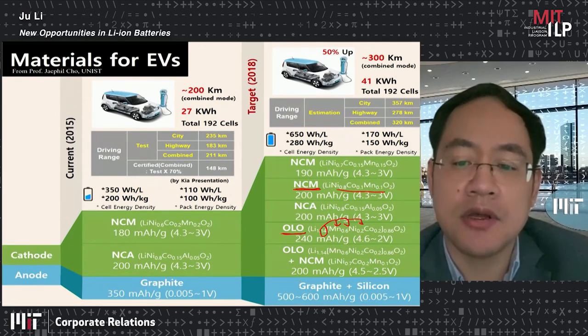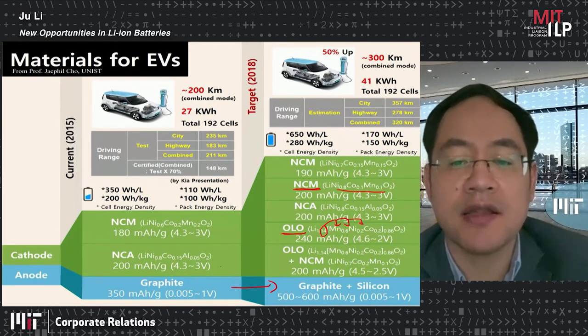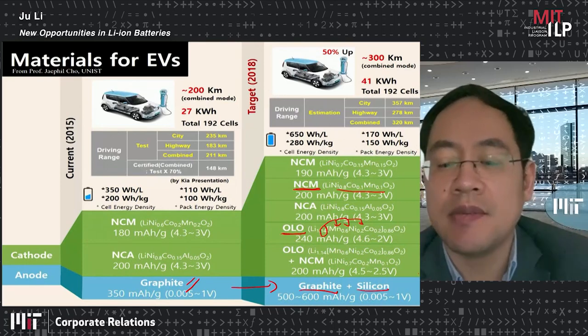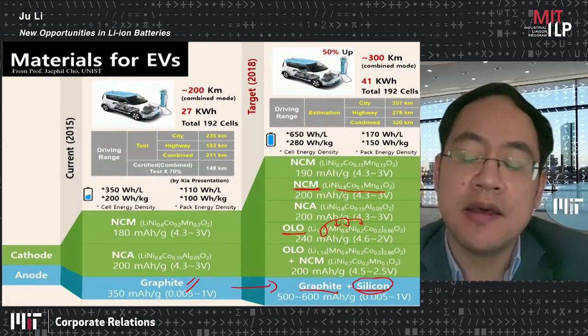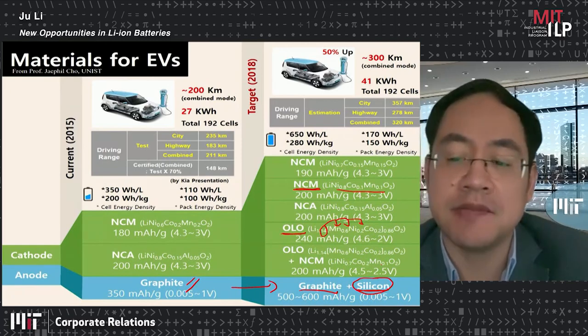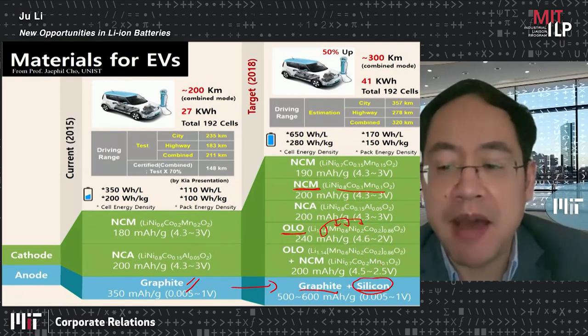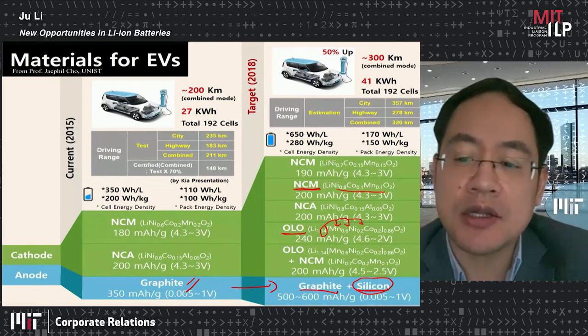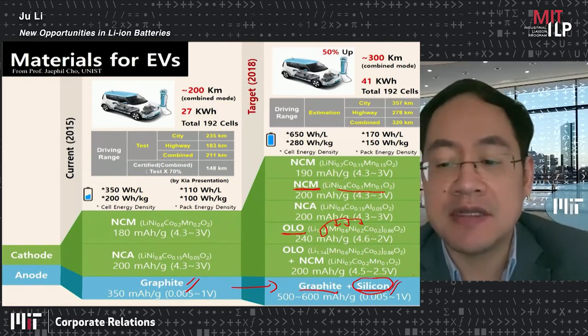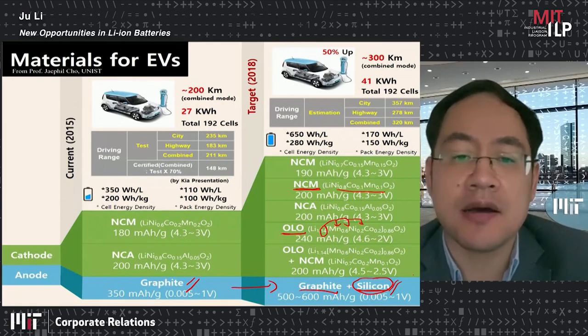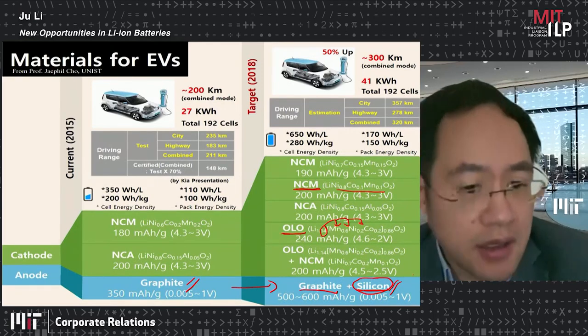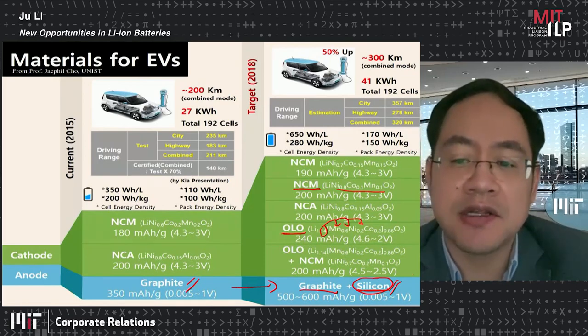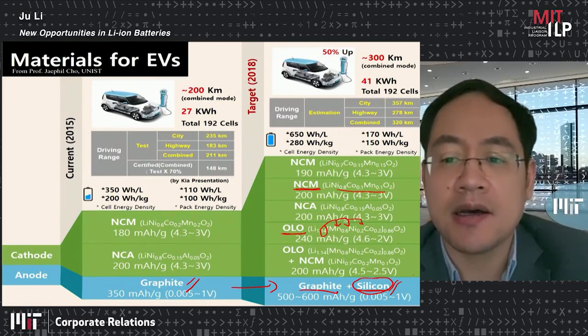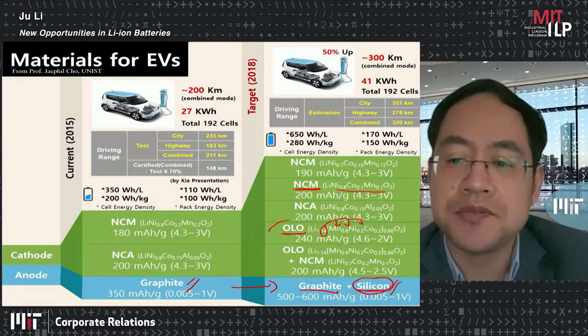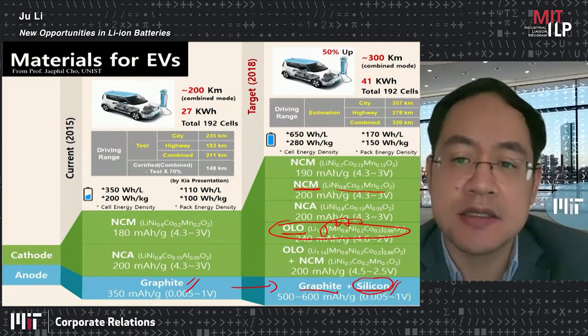And also for the anode, we're going to have going from the pure graphite to graphite with silicon. And of course, due to silicon having a very high volume expansion and generally low Coulombic efficiency, you also need to do some pre-lithiation of the silicon anode. And recently, there's a lot of good work in this area from, for example, University of Maryland, Professor Chunsheng Wang, and I will talk a little bit about this at the end. But we're going to talk about the over-lithiated system.